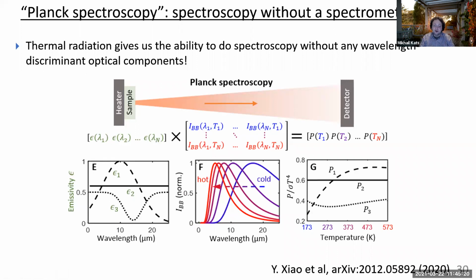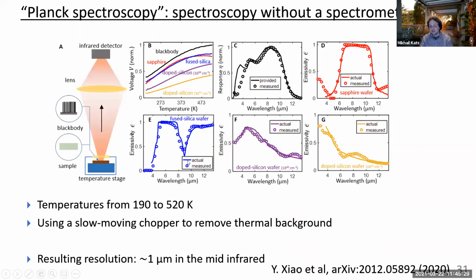And then the other assumption we made is that the emissivity didn't change too fast with wavelength. We assumed it wasn't going back and forth faster than about a micron, because just by playing around, we realized that the technique couldn't resolve anything smaller than a micron anyway. And it turned out that it was easier to do the inverse problem that way. Quite frankly, we're not good enough applied mathematicians to solve this inverse problem the best way possible. We used a linear equation solver in MATLAB and tried a whole bunch of different things, and eventually found a way to do it.